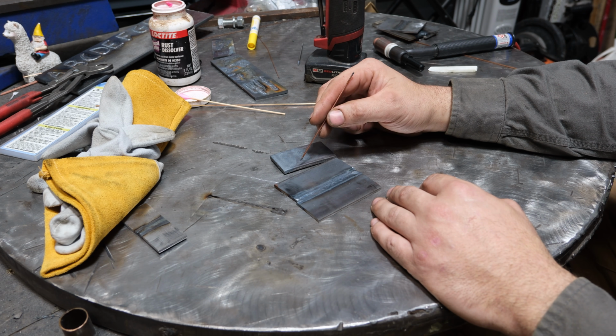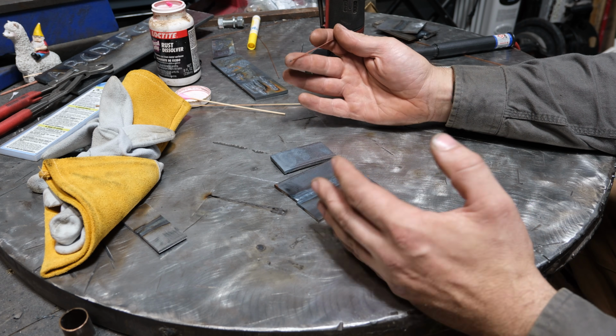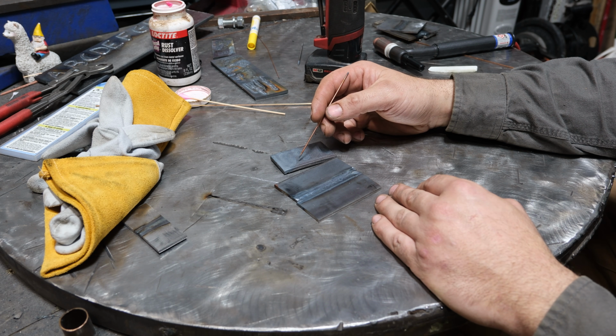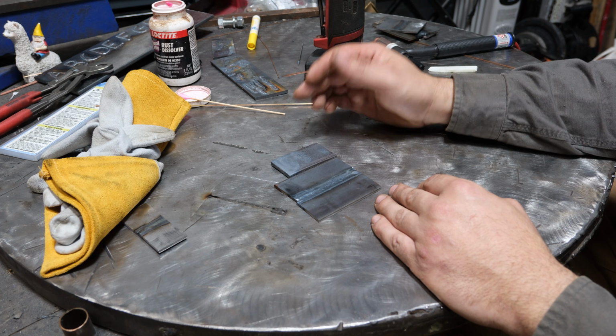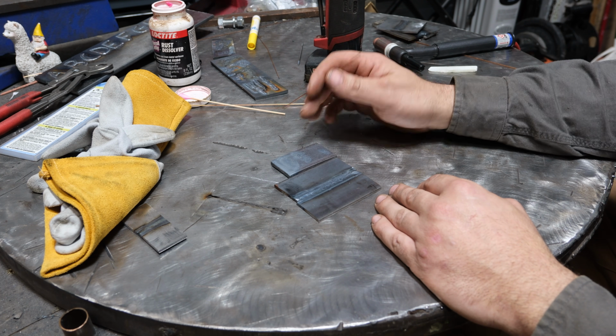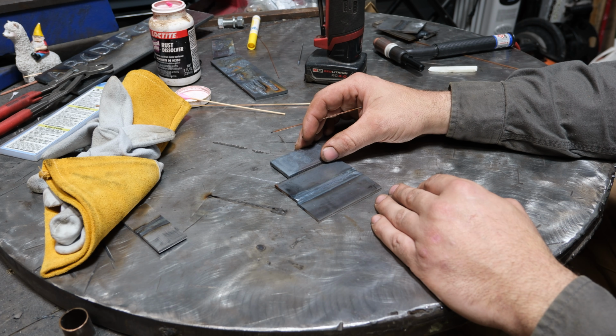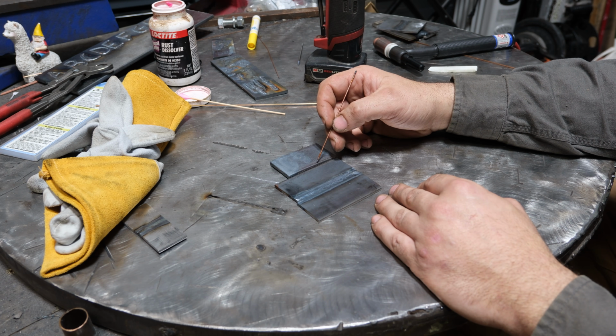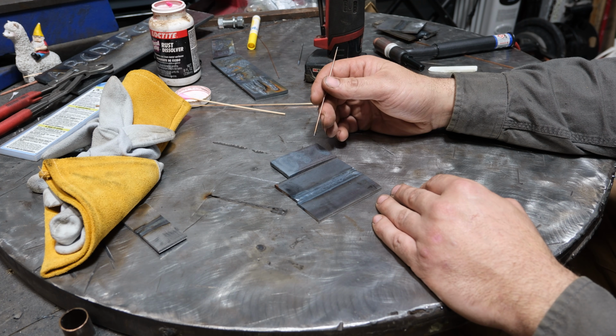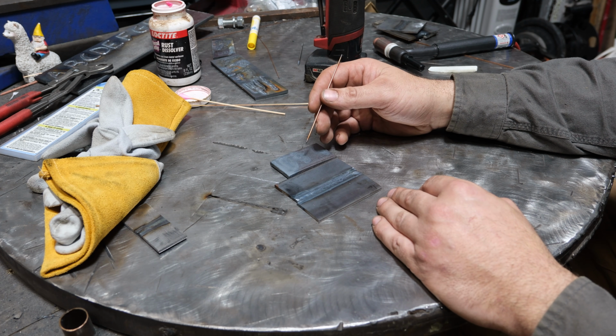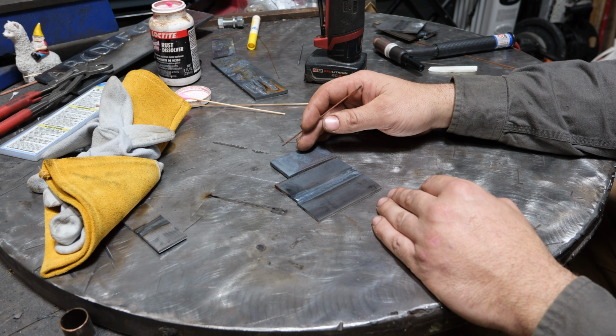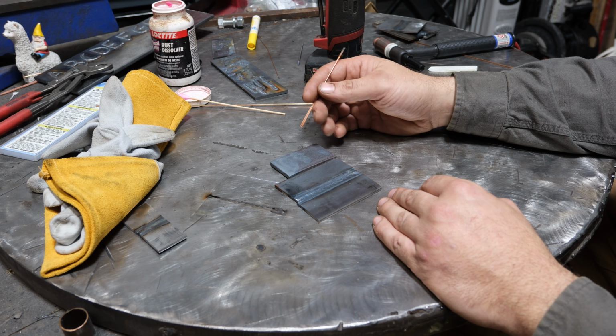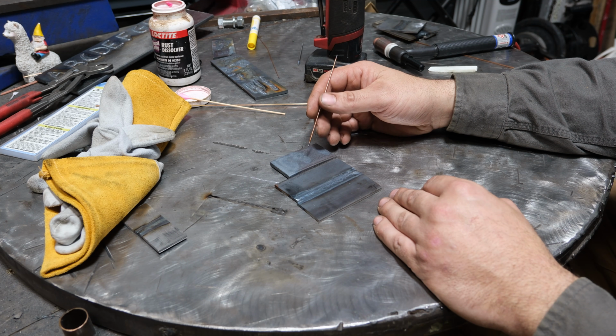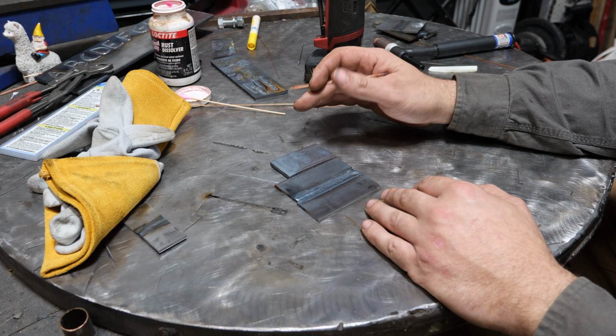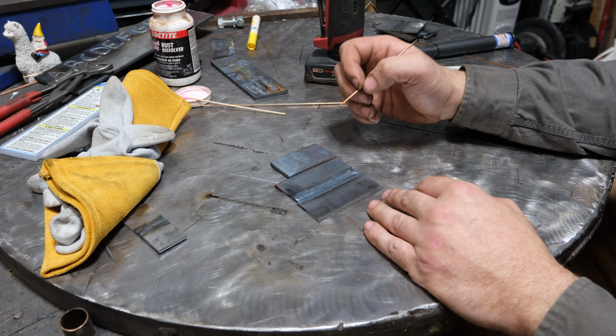Your penetration and fusion is going to be so variable that at the end, you're not really producing anything with any strength. So it is imperative that you maintain proper fit up, which proper fit up means completely tight or a slight gap. It also means beveling thicker pieces, because TIG does not have that much penetration. And if you try and weld 3/8 plate with no bevel, your depth of fusion is going to be minimal at best. It has the least amount of penetration, arguably, of all the processes, especially if you go too fast. So it's all things to consider to get decent results, but I can't stress enough, have proper fit up.